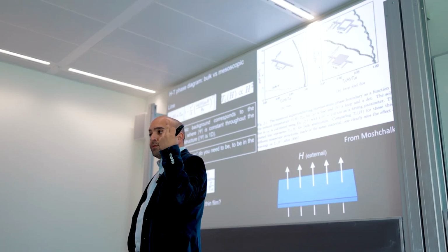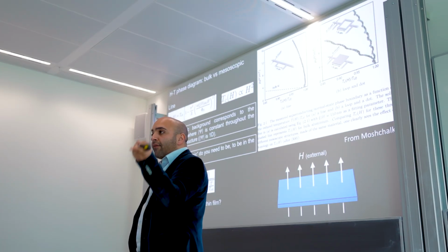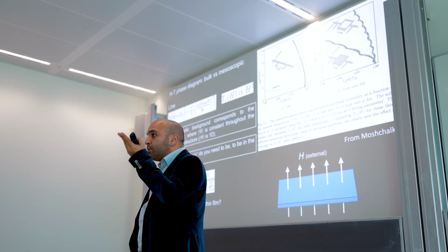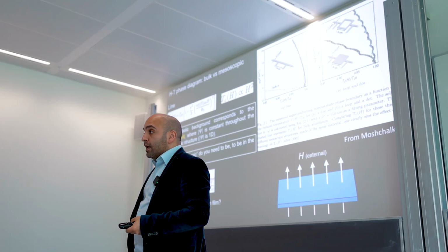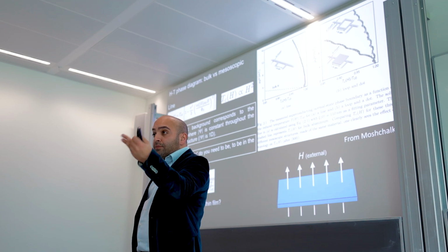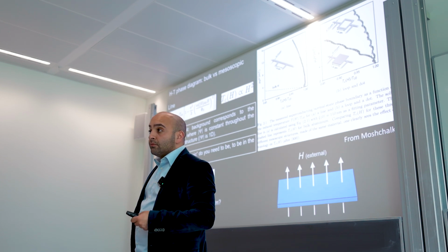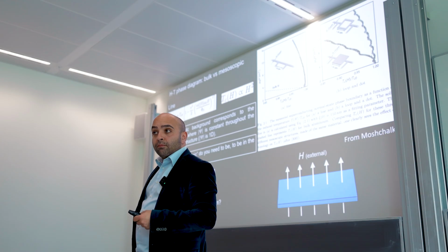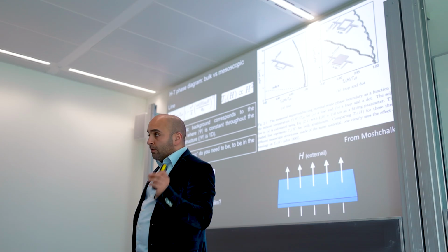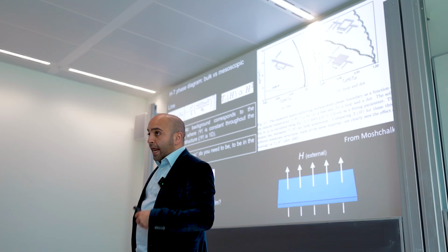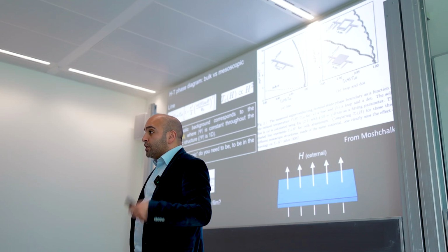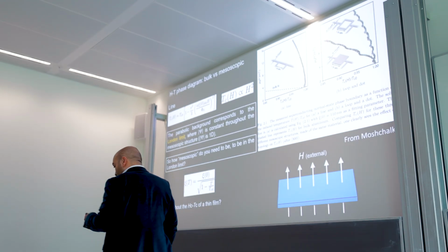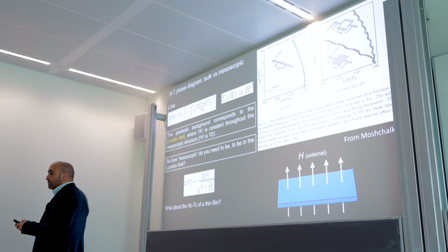So if there is no room, if your superconductor is 1D, it can't have this 2D orbital motion. Cooper pairs can't have that, and therefore you save a lot of kinetic energy, and that shoots up your critical field. It's maybe counterintuitive that making something smaller actually makes it more robust, because it doesn't have room to waste its energy on vortices and orbital angular momentum of Cooper pairs.